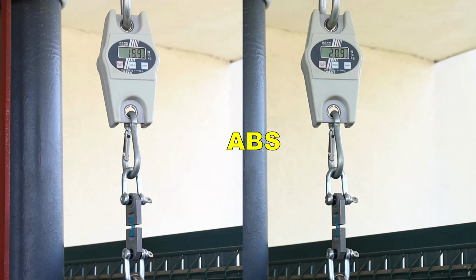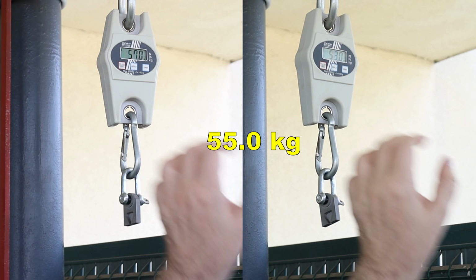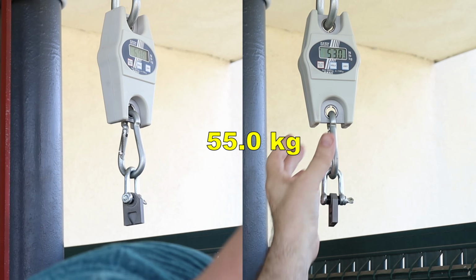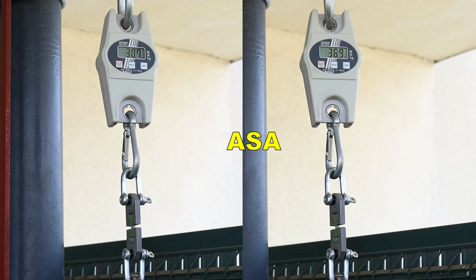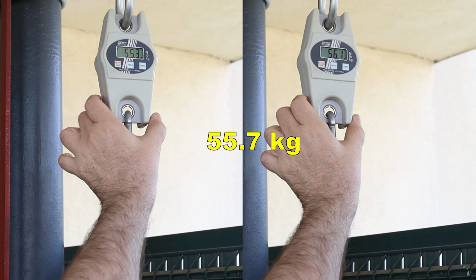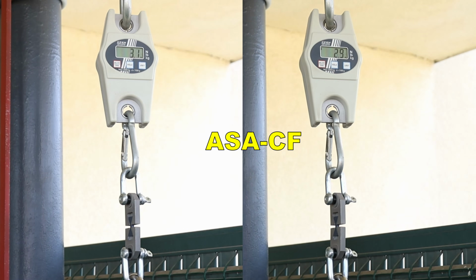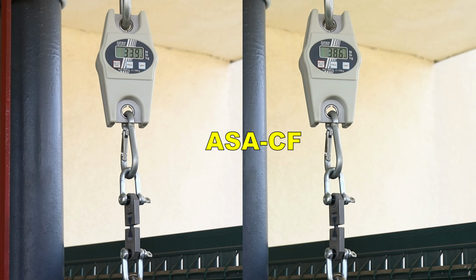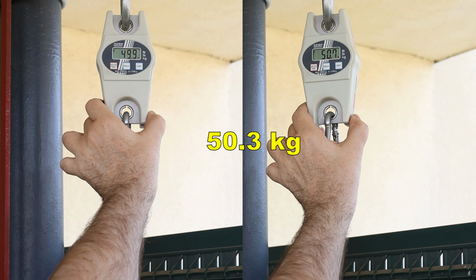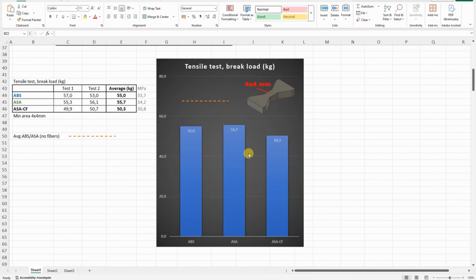Tensile test, ABS. These are horizontally printed objects. ASA. The smallest cross-section area is 4 by 4 millimeters. ASA-CF. In all three cases, the tensile strength is very similar. Interesting, the weakest is the ASA-CF. And here I mark the average ABS-ASA without any fibers, and we can see that all three filaments are a little bit below this line.